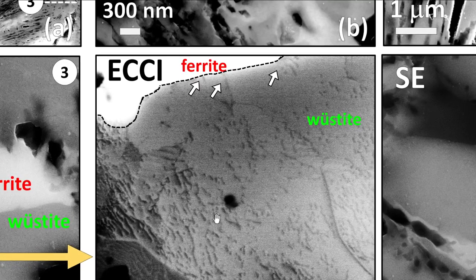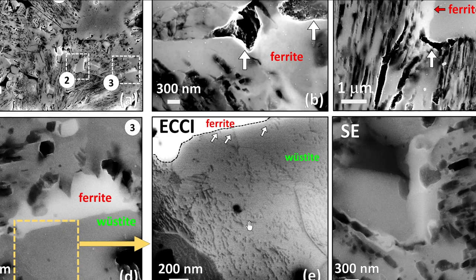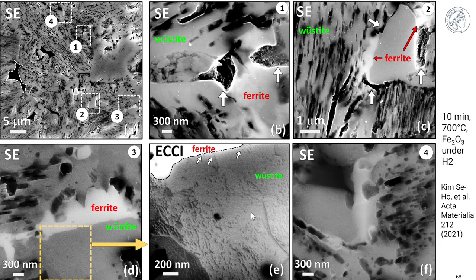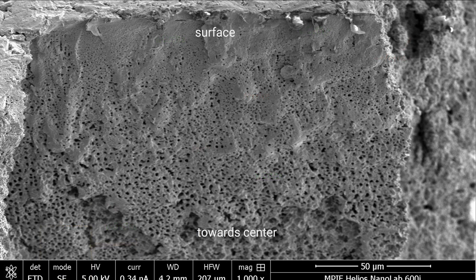And here you see, in the electron channeling contrast imaging, that very complex dislocation substructures form. This has to do with the fact that these different oxide states and also the metal states occupy very different volumes, which gives rise to the fact that you do not only form massive pore structures during the reduction, but you also build up very high stresses.